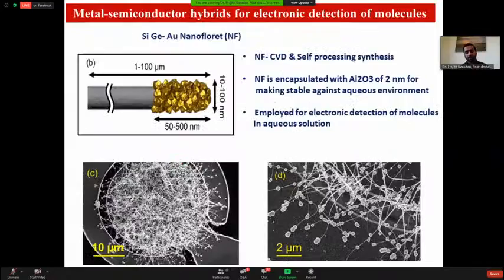Now we are doing some more interesting things, like a metal-semiconductor hybrid for electronic detection of molecules. This is a unique nanostructure which has a gold cap along with silicon germanium nanowires. We call it a nanofloret structure. It is grown by using CVD and self-seeding synthesis. In order to make this structure stable in the aqueous environment, we coated it with Al2O3 of thickness 2 nanometers by using ALD for the electronic detection of molecules.